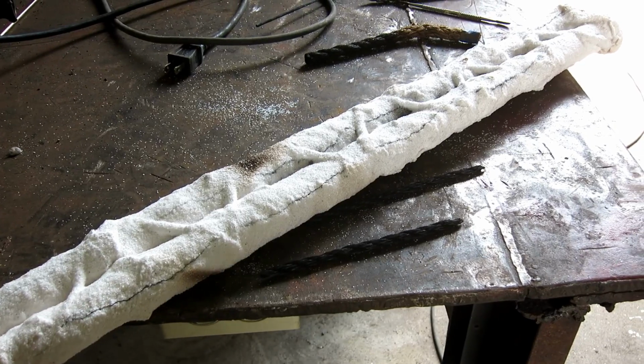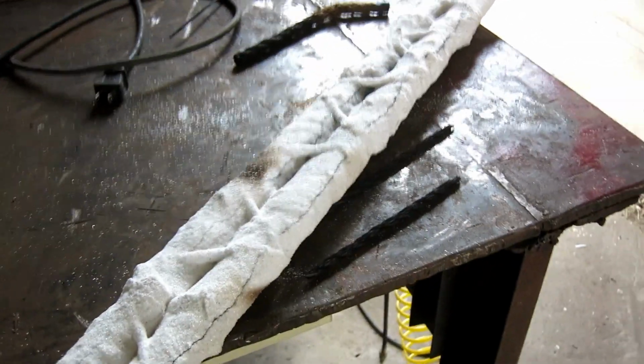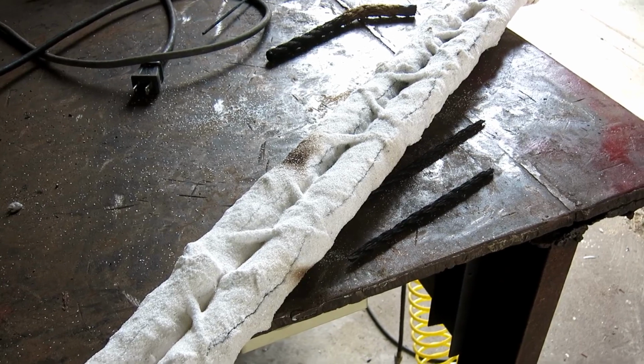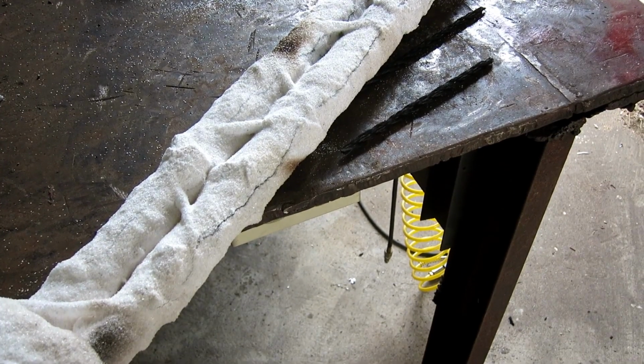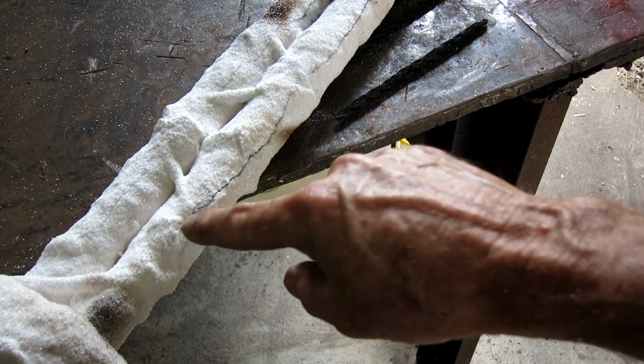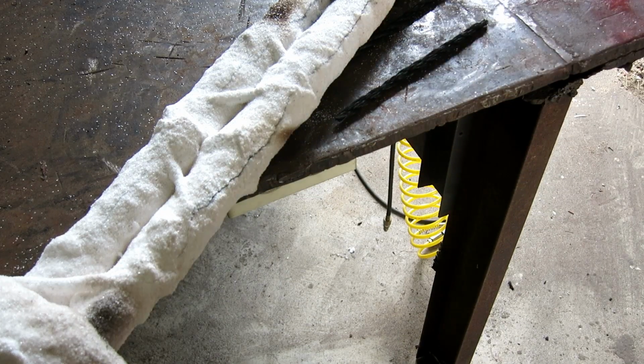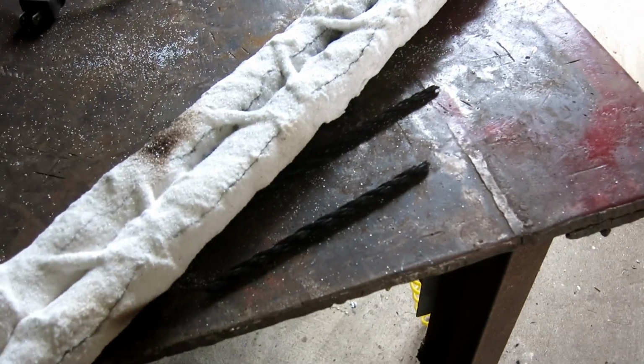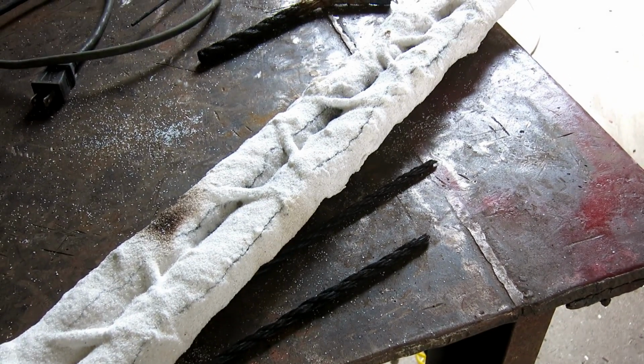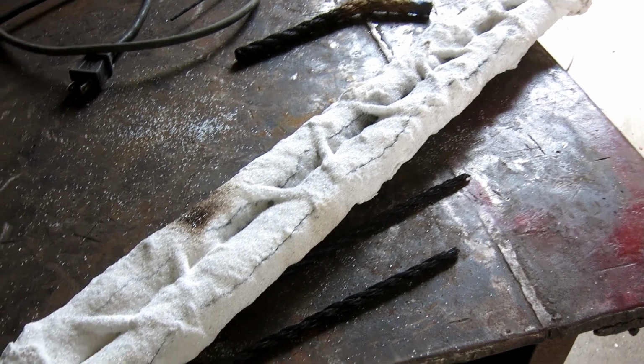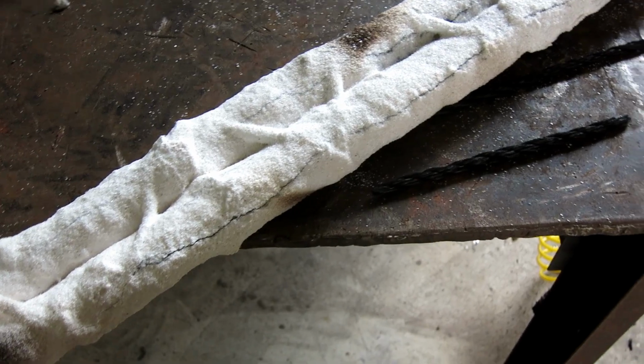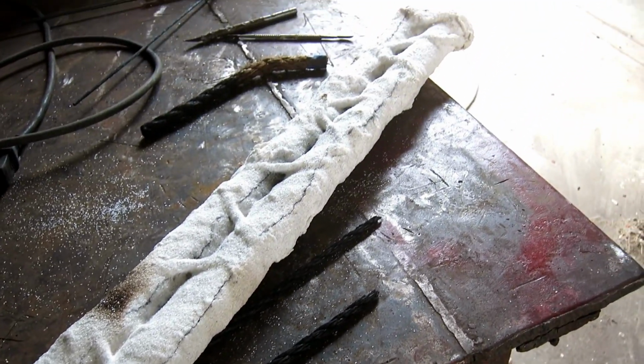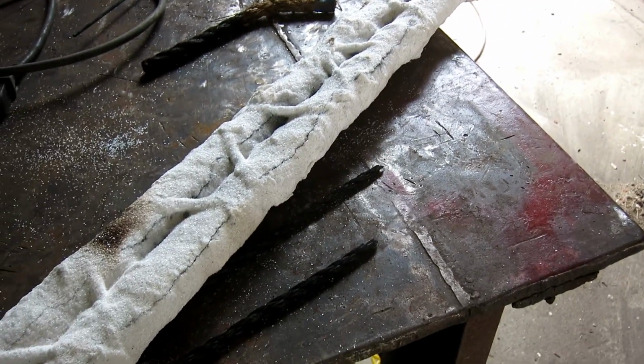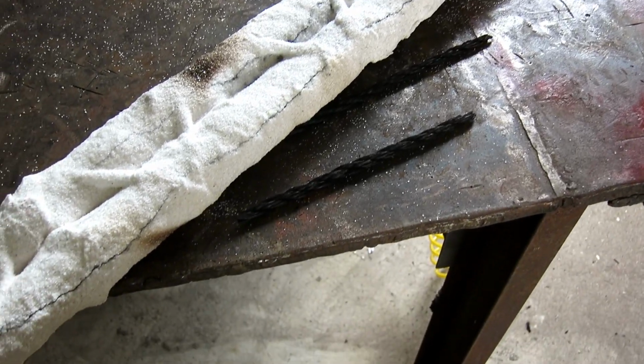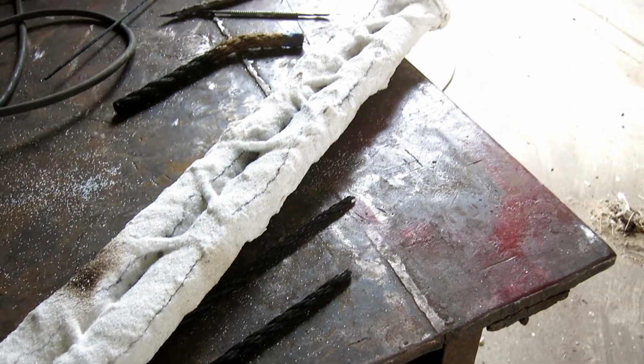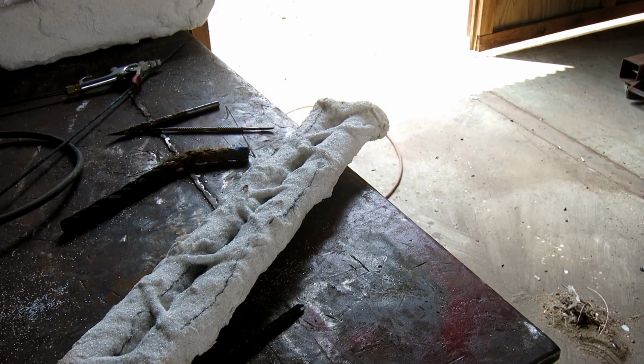Okay, the rope is out totally. I can see from one end to the other, but blowing the compressed air in there with that black carbon, it showed that I have several cracks along the length. So what I'm going to do before I put it back in the kiln to clean out the carbon deposits, I'm going to wrap it with the wire again, and then I'm going to put another couple of coats of ceramic shell on it, just to make sure it's strong. And I have to plug the bottom too, where I cut the bottom off.